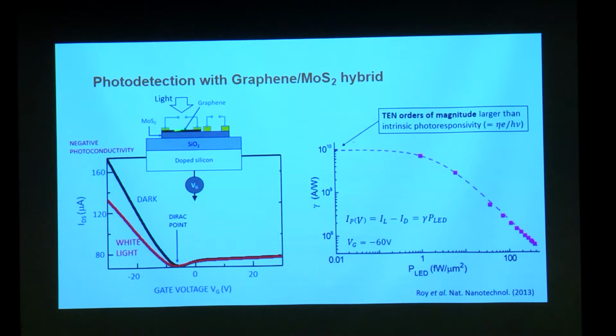and measure the electrical transport through the graphene layer, as a function of the gate voltage, where the gate is right here: in the dark, it's high current, and when I shine light, the current goes down. From the ratio of the change in current divided by the power, it gives us an extremely high responsivity. Typically, a camera in your computer or mobile phone has an intrinsic responsivity of approximately 1 ampere per watt. This is about 10 orders of magnitude larger, which makes it one of the most sensitive photodetectors available today.